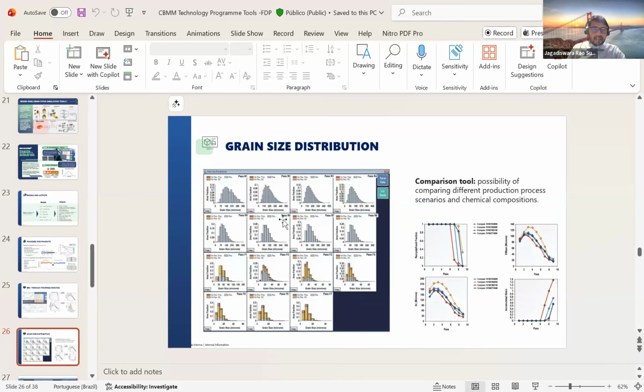If you see the next screen, here we are talking about the example when we start rolling at the roughing mill stage after the reheating furnace. What is the average grain size? For example, on the screen the average grain size is between 70 and 300. When it finishes rolling at the last stage, it is showing around 0 to 20. That means we can get the grain size evolution from the roughing mill's first pass to the finishing mill's last pass, in live conditions as well as before practicing the rolling. If you give the inputs to the model, it will give some idea.